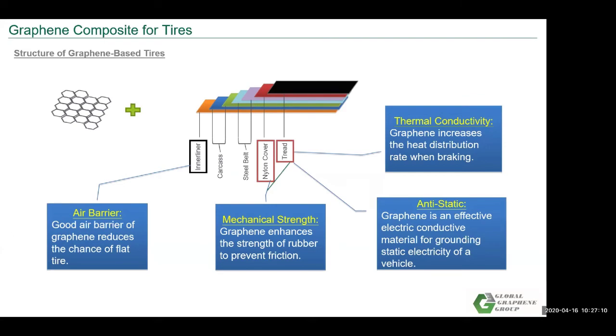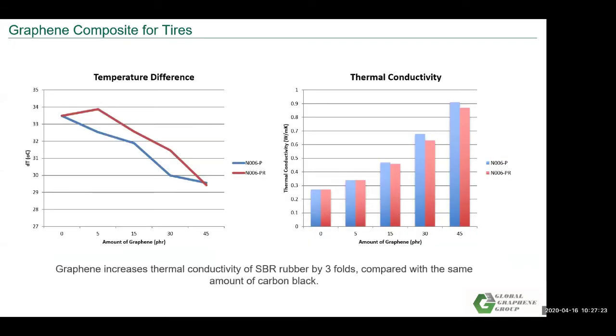And for the outer layer, the strength of the tires, it definitely can help with the thermal conductivity and also can help with the anti-static issues. In this slide, we want to show you that graphene does improve the thermal conductivity of rubbers. With different contents of graphene, the thermal conductivity of the rubber improves from 0.3 to 0.9, which is 3 times better than the pure rubber materials. It's very effective.